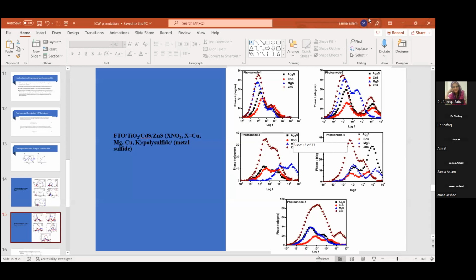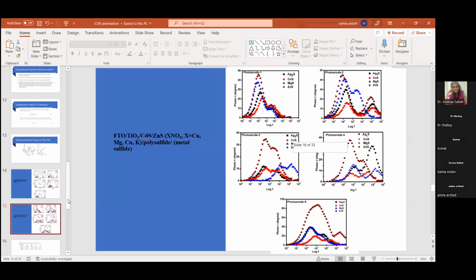It means that with respect to the center of this peak, we can calculate, by using the inverse of this value, the carrier lifetime by using EIS analysis. So in this way, these are the two fundamental parameters which are mainly reported in certain research papers, and how they relate to the charge transport mechanism at various interfaces in EIS analysis. So it is very important, being a scientist working in the solar cell area, that he or she can utilize EIS analysis to explore charge transport mechanism and its influence on efficiency of the solar cells.